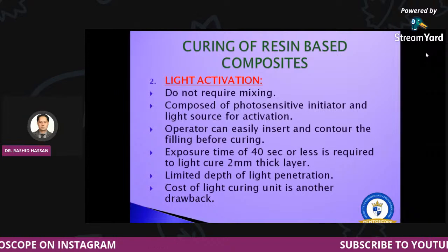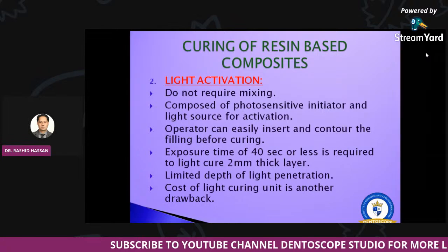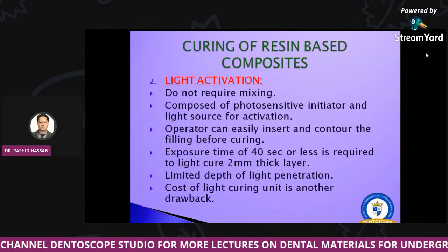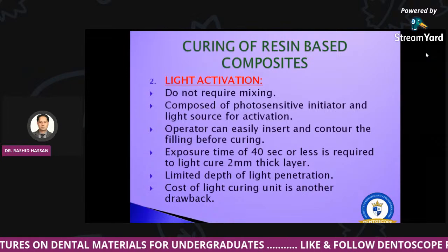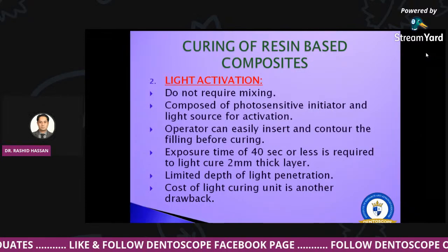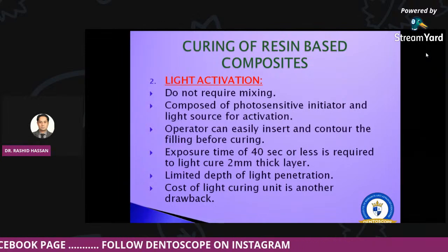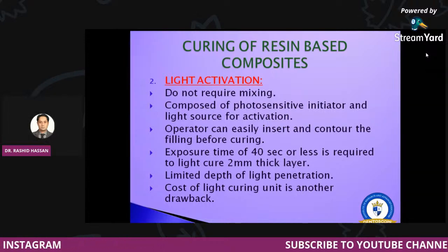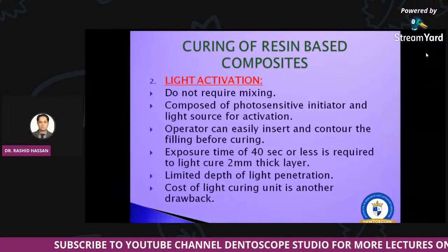Well, an exposure time of 40 seconds or less is required to light cure a 2 millimeter thick layer. Why 2 millimeter? These dental composites are always inserted in increments. Let's suppose you have a 3 or 4 mm deep cavity. You are not going to fill the whole cavity at one time with dental composite. Why? Because the curing depth is only 2 millimeter for dental composite. More than 2 millimeter, it's not going to cure with blue light, right?